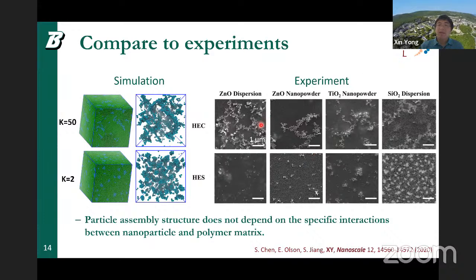And then our experiments demonstrate that this behavior is very consistent for different particle fillers. So we tried zinc oxide dispersion, zinc oxide nanopowders, titanium dioxide nanopowders, silica particles. They all demonstrate very consistent mesostructures in HEC matrix, and then also isolated particle aggregates in the HES matrix. So this behavior is certainly not dependent on specific interaction between particle and polymer matrix, which supports our explanation that this is due to a physical effect that's generated by the chain conformation, which is more like an entropic effect.